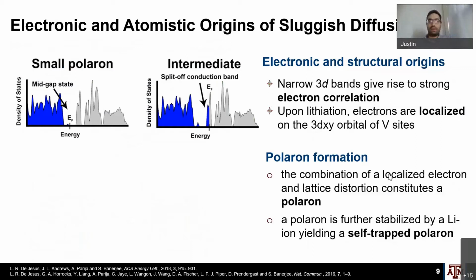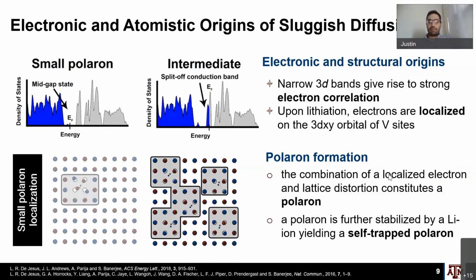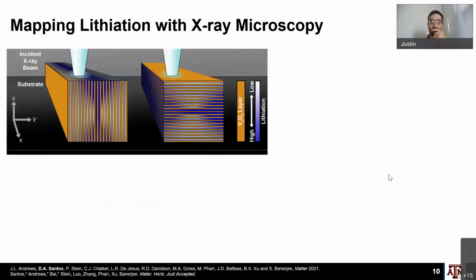And so when you put these things together, you think about the sluggish ionic diffusion and the sluggish polaronic diffusion, the electronic diffusion through these materials. What really is happening in these materials is that there's this self-trapping of a polaron that takes place. So the electron that is given to the V2O5 lattice when lithium intercalates gets localized on a very specific vanadium orbital, the dxy orbital, and it's very stabilized when it's in. So the lithium ion is stabilized within the lattice when it's in close proximity to that polaron, and so really the self-trapping of lithium presents an issue in terms of the coupled polaron-ion diffusion.